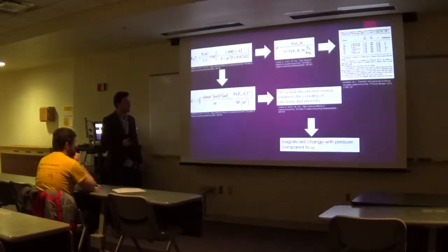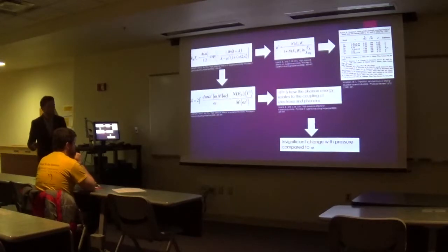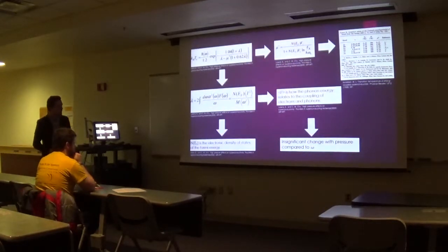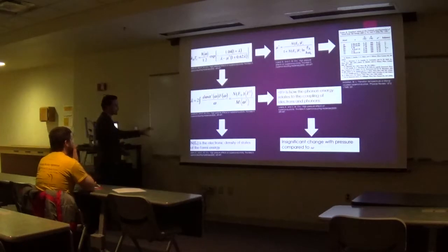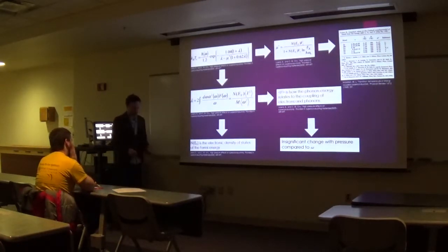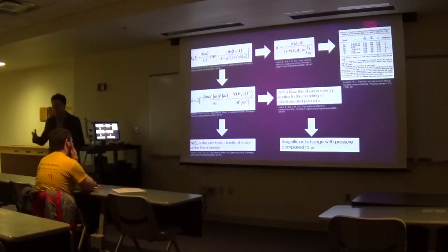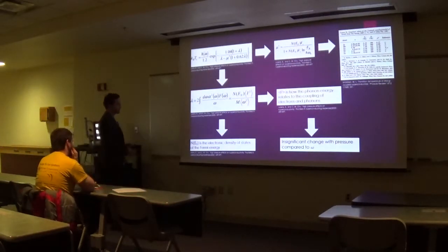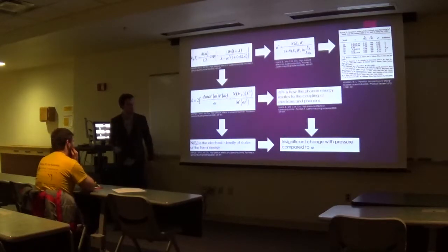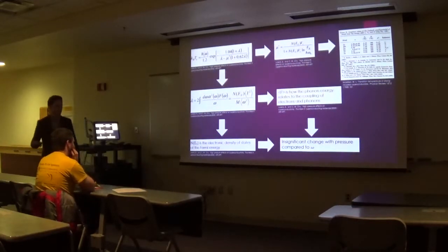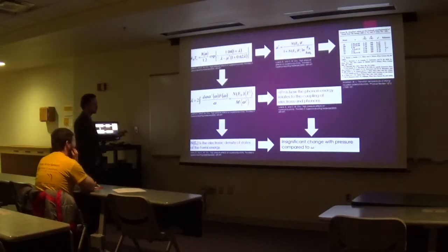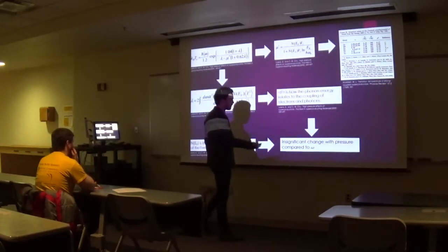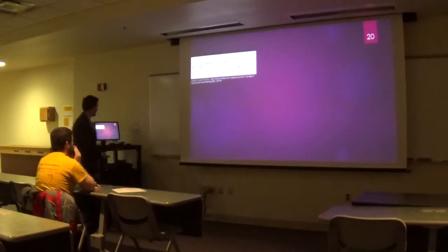What we find is relatively insignificant changes when we impose pressure. So let's look at this N(E_F), the electronic density of states at the Fermi energy. We can just think of density of states as a population of electrons around the Fermi energy. Again, insignificant change with pressure. So I think you know where this is going, right? Insignificant when compared to our omega, our phonon frequency. Let's go back to this lambda right here.